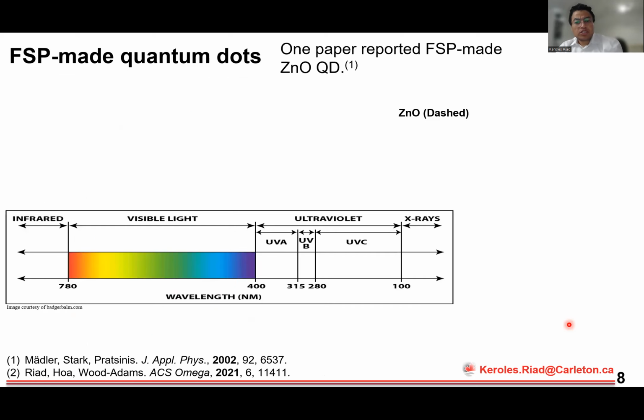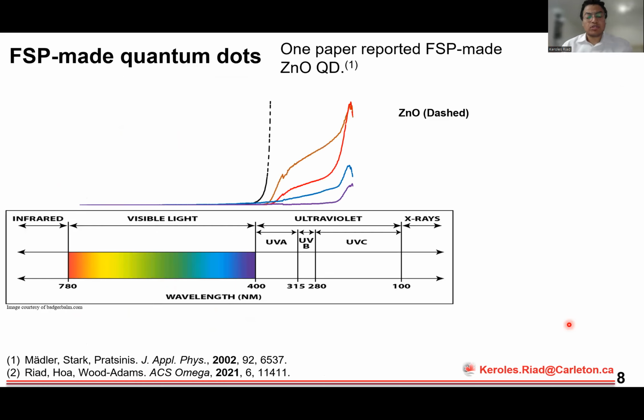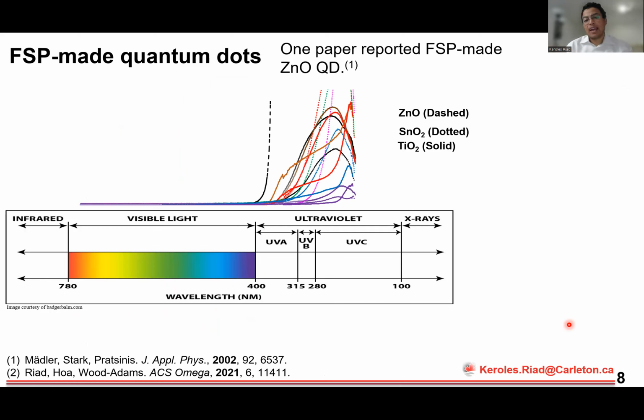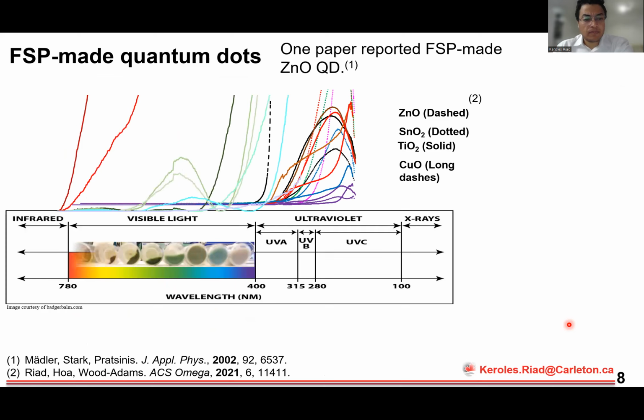Essentially, just by selecting the right semiconducting material and the silica loading, we're able to make quantum dots with any band gap energy between the UVC region all the way to the dark red part of the visible spectrum using the FSP scalable synthesis process.